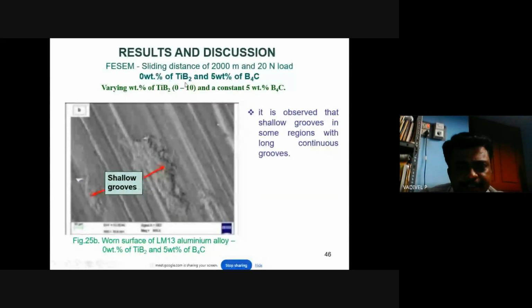And this is with only 5% of boron carbide. Here you can see the shallow grooves in the wear test. The wear test of this 5% boron carbide sample gives shallow grooves in each place.